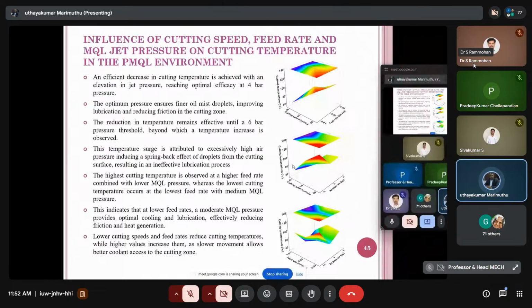The reduction in temperature remains effective until the 6 bar pressure threshold, beyond which a temperature increase is observed. This temperature surge is attributed to excessively high air pressure inducing a spring-back effect of droplets from the cutting surface, resulting in an ineffective lubrication process. The highest cutting temperature is observed at the highest feed rate combined with lower MQL pressure, whereas the lowest cutting temperature occurs at the lowest feed rate with the medium MQL pressure, and so on.